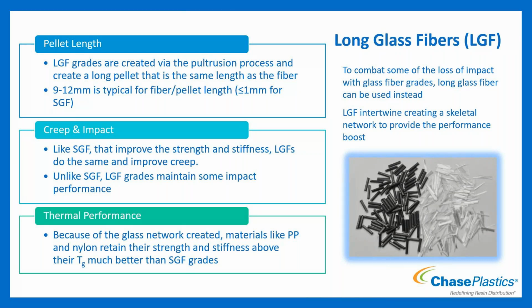One way to combat that is to use long glass fiber. When long glass fiber is used, it intertwines and creates a skeletal network that provides a performance boost to the material. Because of that, when it's impacted or hit, it distributes that energy throughout the whole skeletal network of the long glass fiber, versus short glass which just hits and breaks. So you see a boost, or a maintaining, of the impact performance that you don't get with short glass.